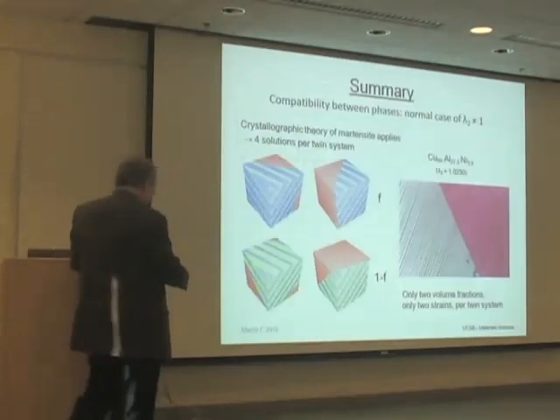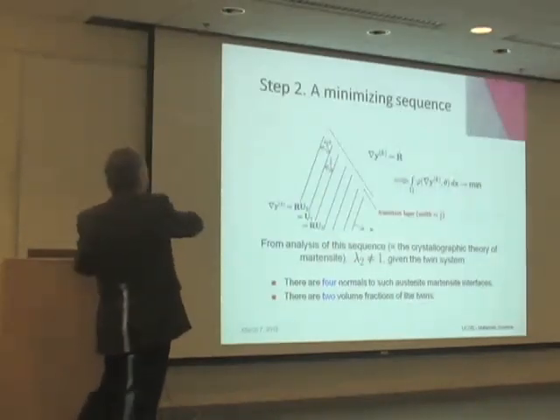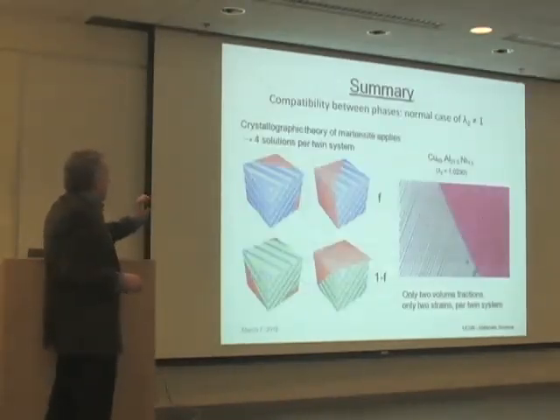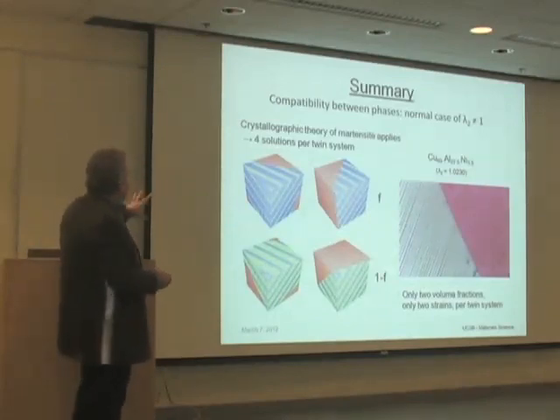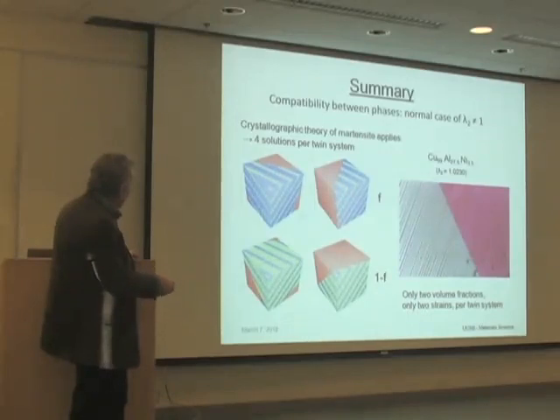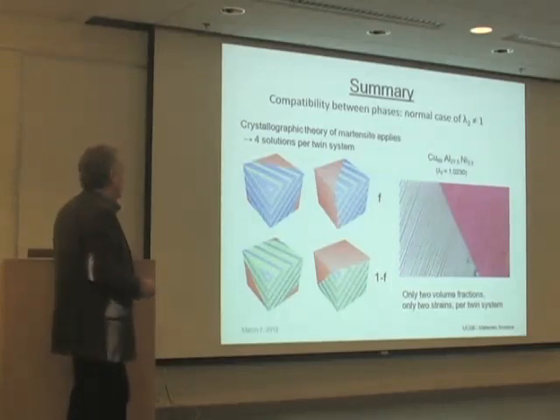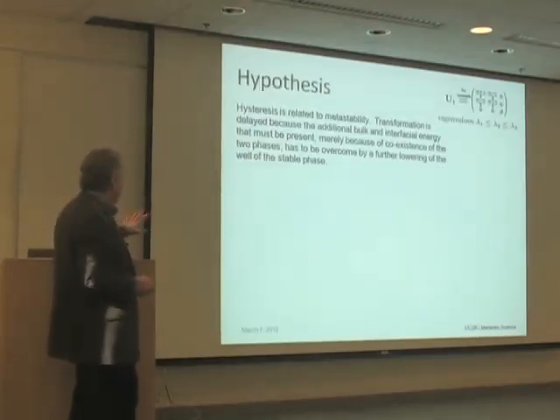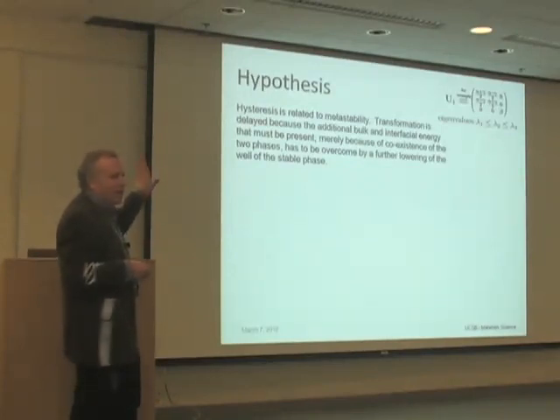Okay, very good. First of all, there's a summary of the crystallographic theory. It says that there are 4 solutions to twin systems. Those are the analytically calculated solutions. One of those solutions agrees very well with that picture, with the corresponding 2 volume fractions, and so forth. So for this hysteresis, we believe that it's due to that leftover energy in that interface, both bulk elastic energy and interfacial energy, the sum of the two.